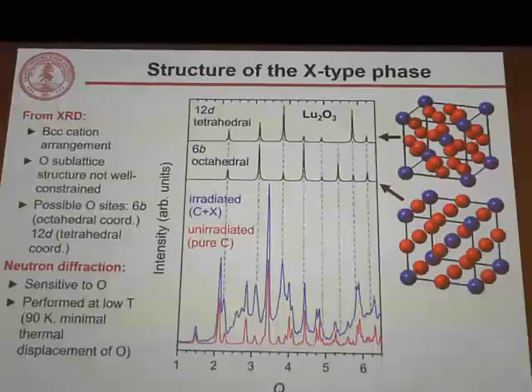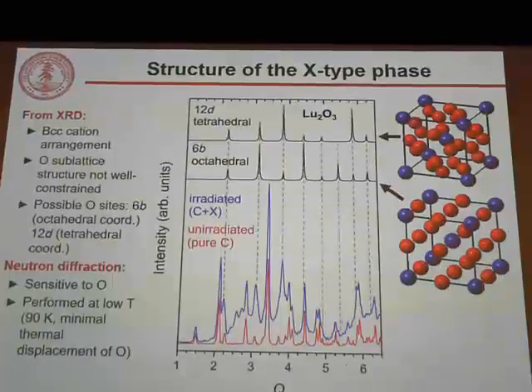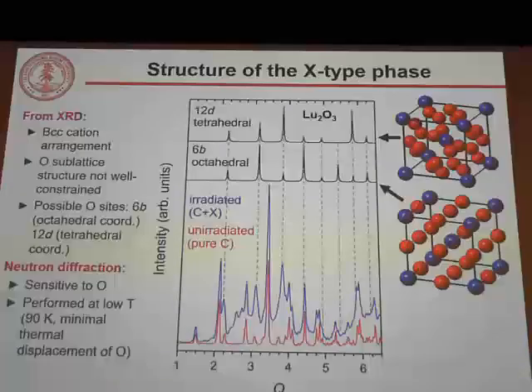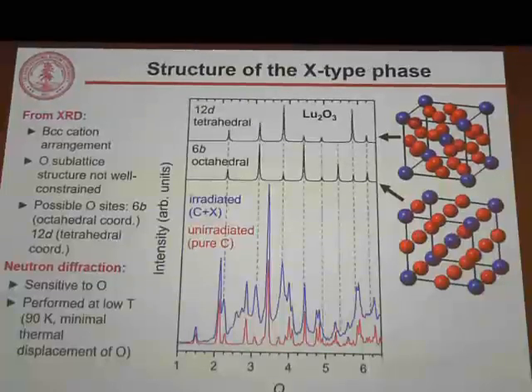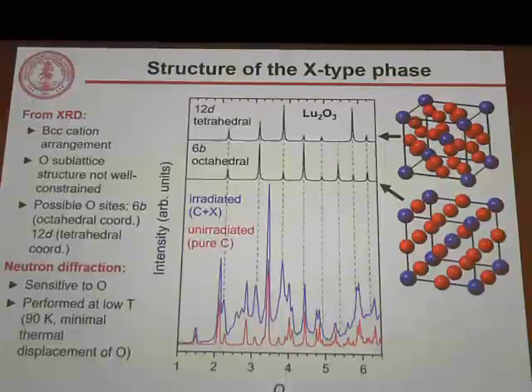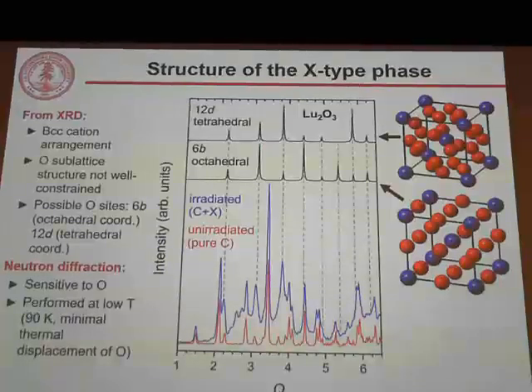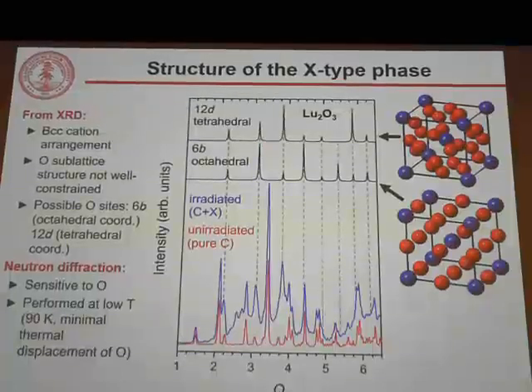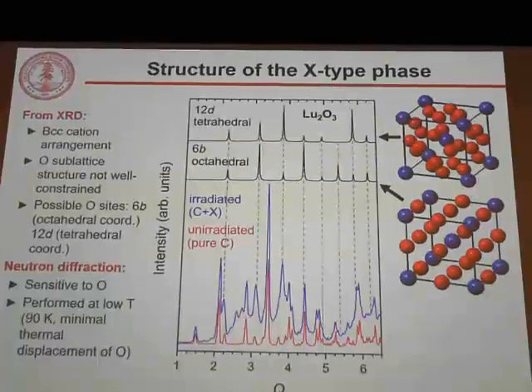So I show in red the neutron diffraction pattern from an unirradiated material, and in blue the neutron diffraction pattern from an irradiated material, as indicated by these horizontal dashed gray lines. There are new peaks that emerge after irradiation corresponding to this X-type structure. We can compare the intensities of those peaks to these black lines on top, which are the simulated diffraction patterns of these two potential structures. And we see that the match of the experimental data is great for the structure with oxygen in the tetrahedral site and poor for that of oxygen in the octahedral site. So we've solved the structure of this material now.